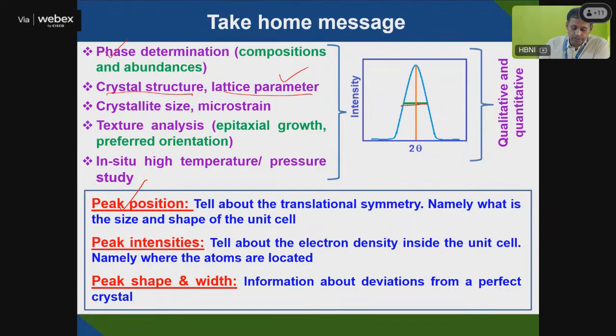So the peak position will give you translational symmetry, namely the size and shape of the unit cell. From the peak intensity you will get the electron density inside the unit cell, namely where the atoms are located, whether FCC, BCC; the atom location you can easily find out using peak intensity. And peak shape and width give you information about deviations from a perfect crystal. If it is a perfect crystal, then you will get a sharp line peak, but in case of nanophase, you will get a broad peak. So these are the information mostly you will get from XRD instruments.